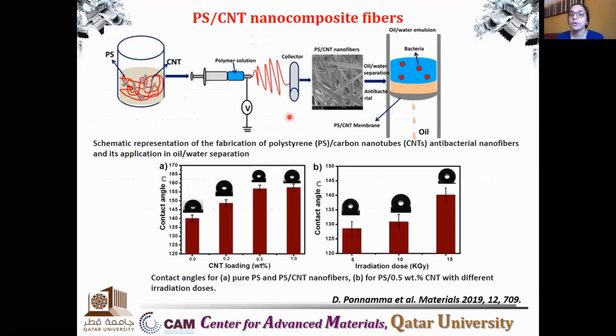So first of all, I'd like to introduce some nanofibers that we made by electrospinning based on polystyrene and carbon nanotubes. And you know that polystyrene is a hydrophobic polymer, and in the same way, carbon nanotube is also very notable for its hydrophobicity. So we thought in the beginning, why don't we combine this hydrophobic polymer and the hydrophobic nanofiller to make a super hydrophobic nanocomposite fiber that can effectively separate oil and water. But this was the problem. Our material became super hydrophobic, so it could not separate oil water mixture. Rather, it absorbed the oil molecules. So these are the results. And we made polystyrene and carbon nanotube fibers by electrospinning process, and this shows the fiber structure.